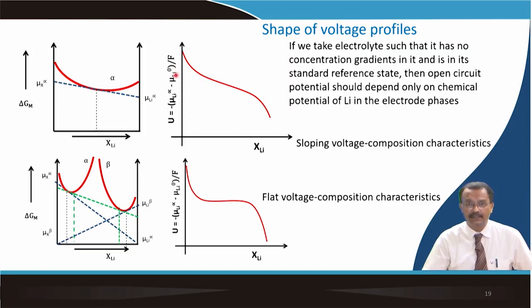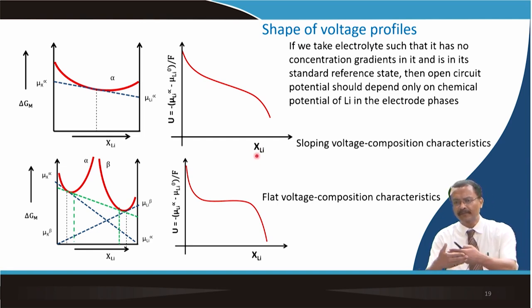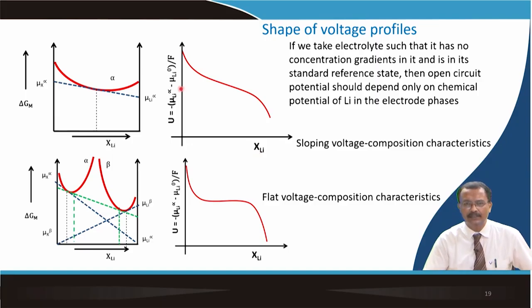So, this is the expression that you are having, and you can see that if you have a solid solution, then you have a sloping voltage profile. As you put more lithium during your discharge into the cathode, then you will see this kind of sloping voltage. But instead, if you have a two phase mixture, then we will prove later that it will give you a constant kind of voltage, and then it will fall here and here. So, the shape of the voltage profile can be related with the free energy versus composition diagram.